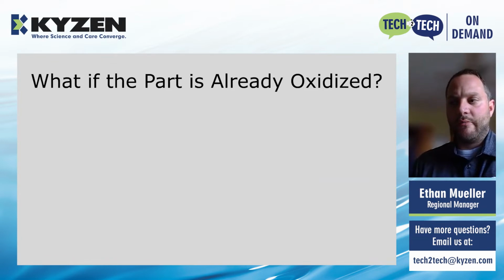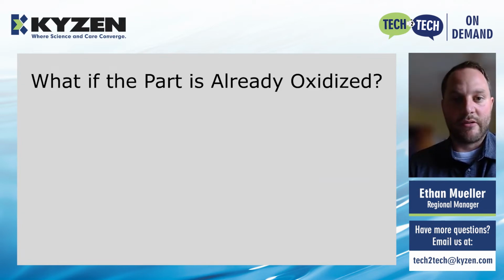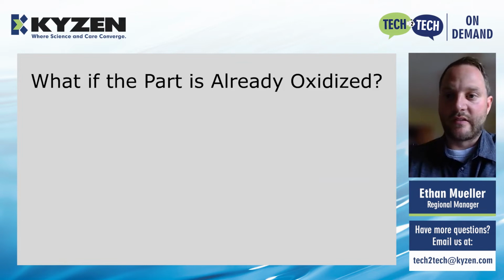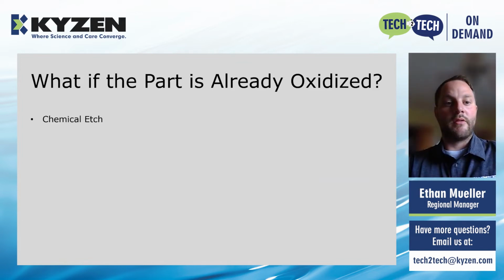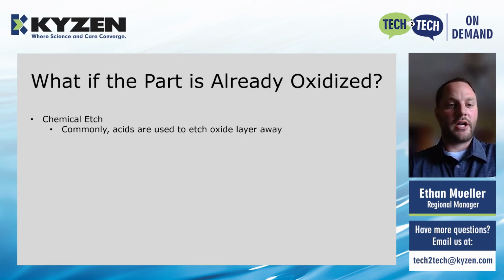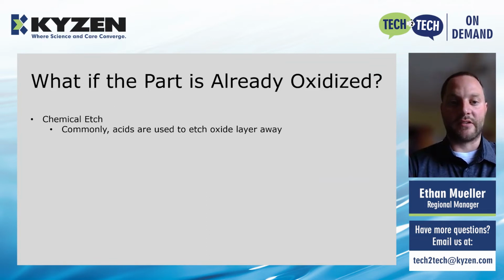So maybe you're dealing with a situation where your parts are already oxidized, and that's not unlikely. People deal with that every day. There's multiple different ways you can go about it. One of the very common ways is doing a chemical etch. Very typically, acids are used to etch away the oxide layer to expose that base metal. And so you can go ahead and do your plating process or your painting process or whatever it is you're going to do.